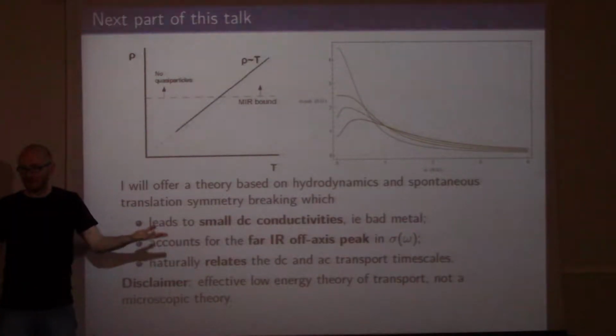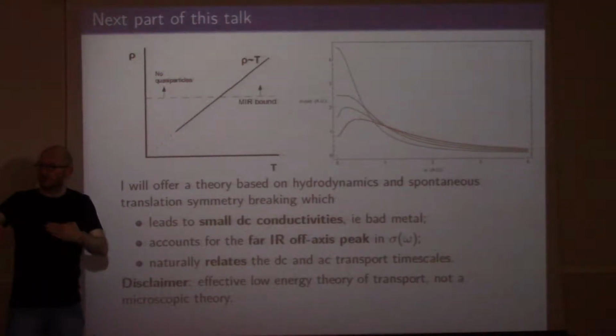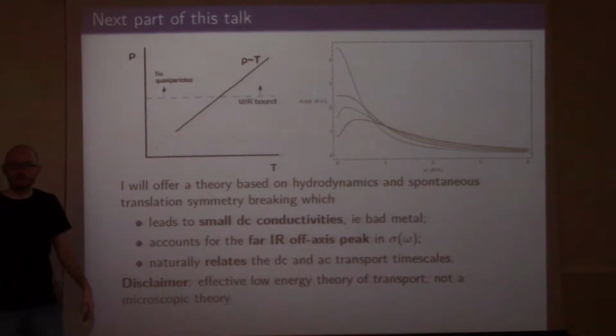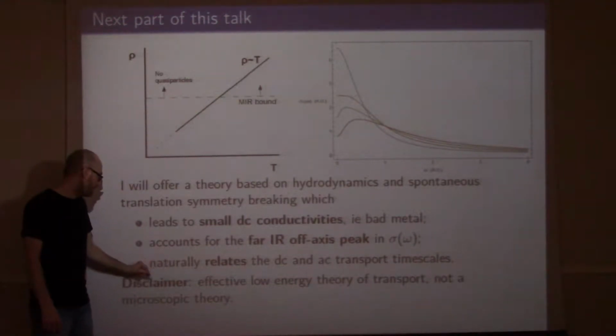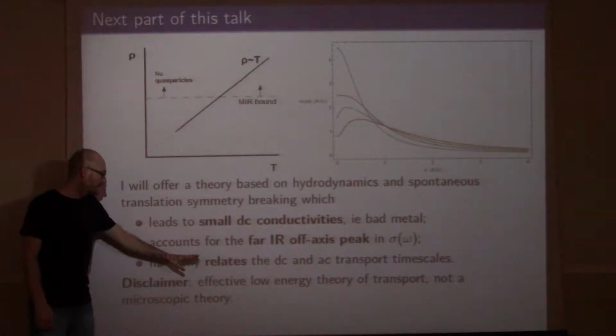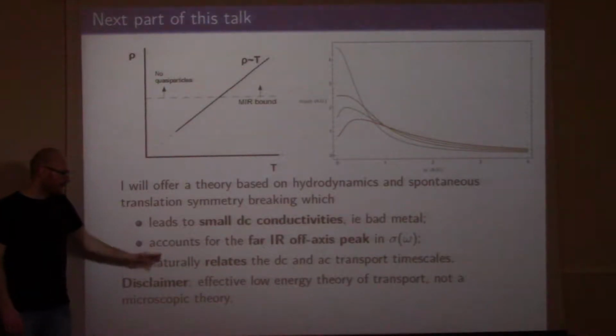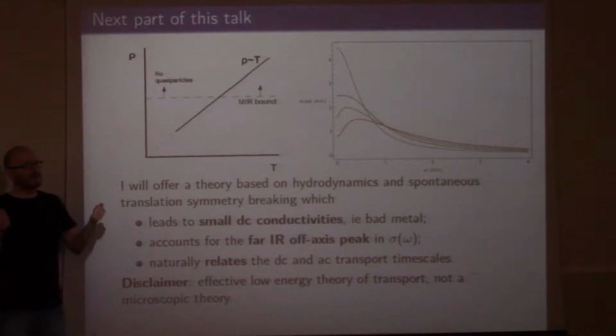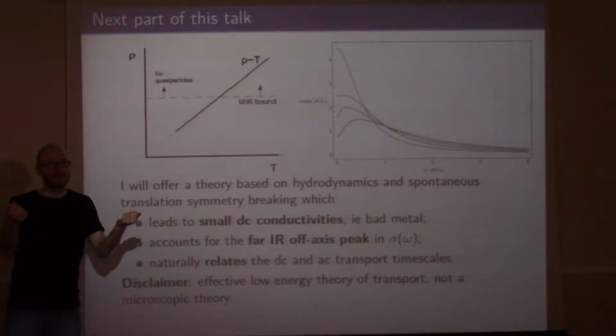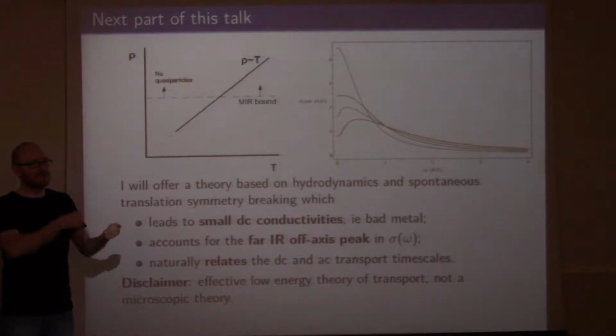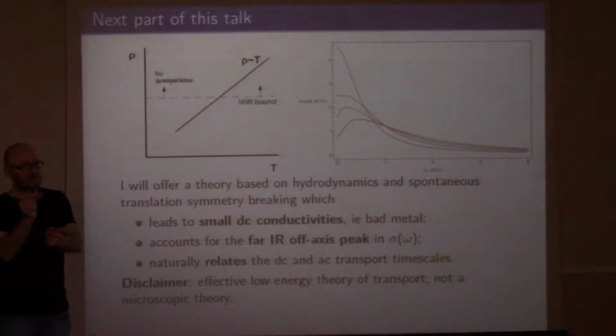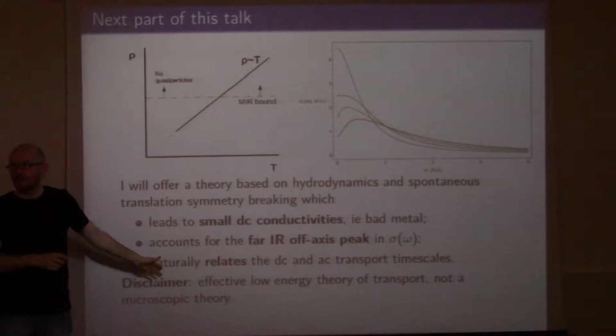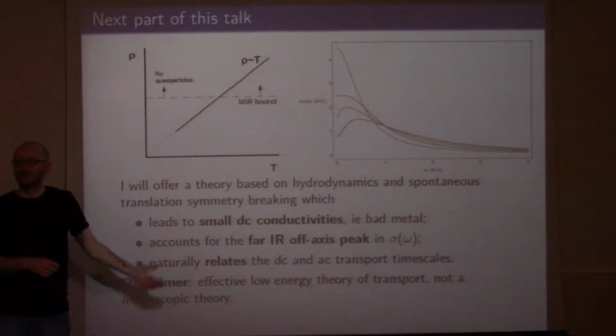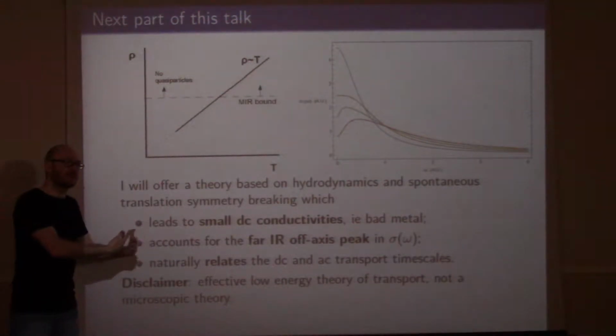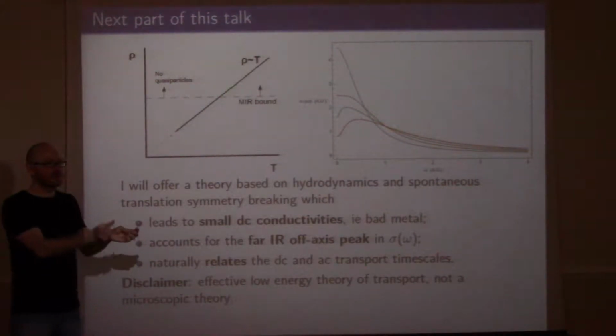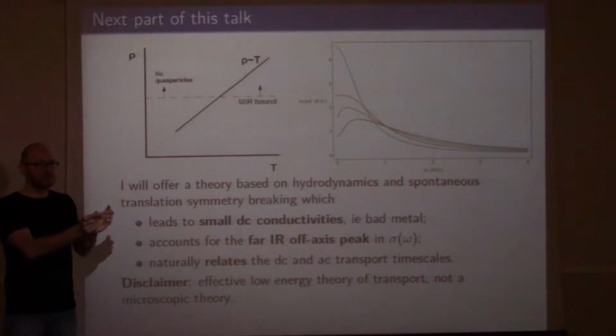It might not be the right one, but it certainly gives a mechanism by which you can see a peak moving off axis in the frequency-dependent conductivity. And also we'll play a game at some point where we see that we can naturally relate the timescale that governs the DC resistivity and the location of this peak. And it won't explain why that timescale is the Planckian timescale, but it will give some mechanism by which these two timescales can be understood to be the same.